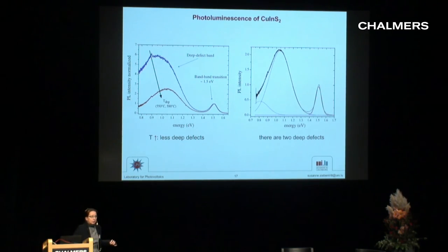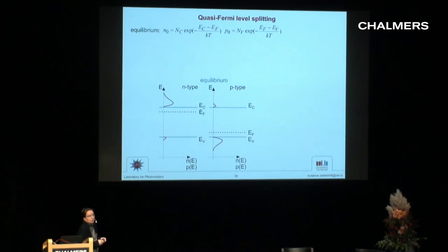And it's bad for the solar cell because it takes away the electrons from the high energy level, and the electrons cannot contribute to the open circuit voltage of the solar cell. Now, we have a way to look at the open circuit voltage of the solar cell before we make the solar cell, and this is by photoluminescence. We can measure the Quasi Fermi level splitting.